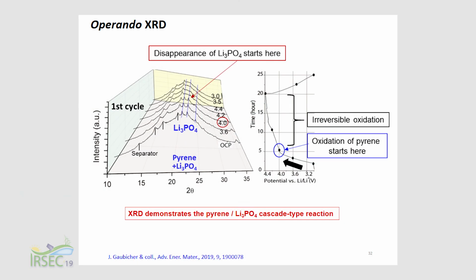So we have done some different kinds of experiments. From operando XRD in electrodes with the two additives, you can see that the diffraction lines of Li3PO4 disappear exactly at first charge, they disappear exactly at 4 volts. And 4 volts is exactly the voltage at which pyrene begins to oxidize. So this is a very nice demonstration of the cascade reaction mechanism. As soon as protons are released, they are consumed and Li3PO4 disappears.